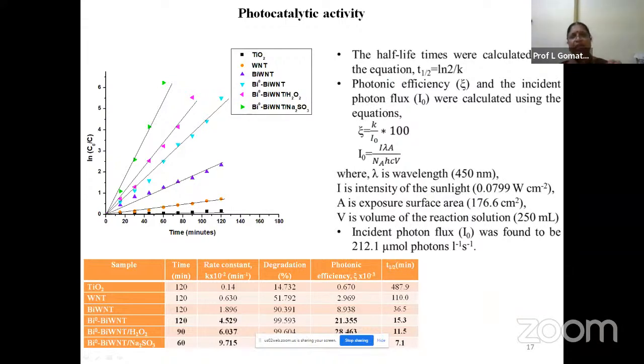But in addition to this catalyst, we have added some reagents, that is H2O2 or Na2SO3. Whatever time it has taken to degrade the pollutant is given here, and the rate constants are also mentioned in the second column. We can observe that the rate constant was around 4.5 into 10 to the power of -2 for the BI0 BIWNT sample, and it increased with the additional electron acceptors in the reaction solution, like H2O2 and sodium sulfite.